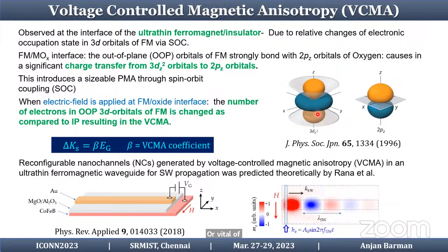So here you can see the ferromagnet and oxide interface, where the ferromagnet has this 3d z-square band, and the oxygen has this 2pz band, and they actually hybridize, and there is a charge transfer between the 3d z-square and 2pz, and that introduces a sizable perpendicular magnetic anisotropy through spin-orbit coupling.